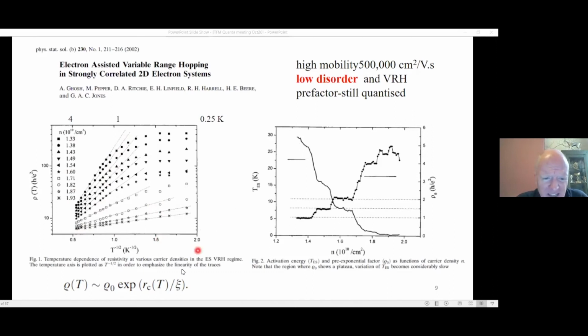And when the data was looked at in a little bit more detail, it was found that the prefactor, although it was quantized, actually changed in steps of a half h over e squared. So when you looked at this in more detail, it was even more interesting that there was structure to this prefactor.